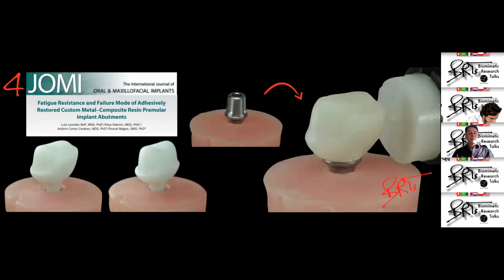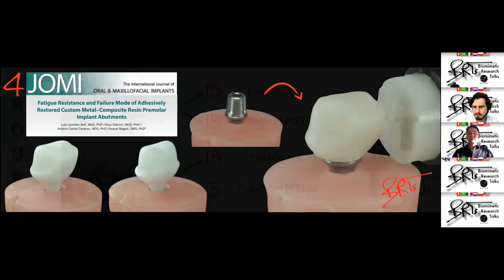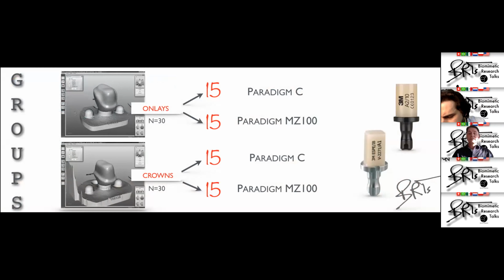In the fourth article, we went beyond. We built a composite resin, or at the time, and now a hybrid composite-metal abutment, copying the ceramic one, and we tested the fatigue resistance of these hybrids restored with composite resin and ceramic. We published this article in 2014. This experiment is basically the same. We worked with 30 onlays and 30 crowns, where we bonded 15 ceramic and 15 composite resin restorations.